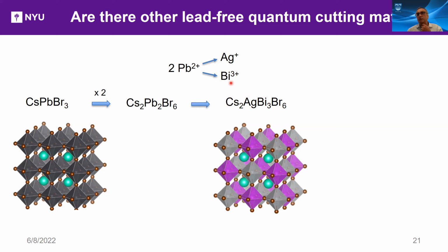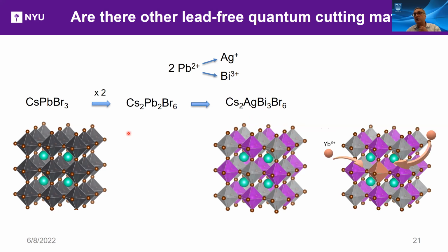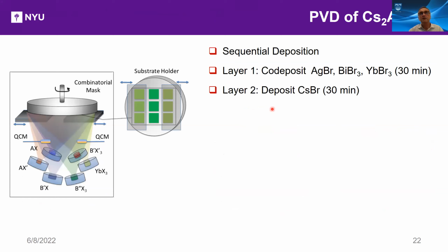So the compound that we're talking about is called a double perovskite, because it comes from this derivative by doubling the unit cell. And we're going to do ytterbium doping, and ytterbium can substitute into either the bismuth or the silver. If it does substitute into the silver, it might have to form defects as well to keep the vicinity charge neutrality, whereas it's an isovalent substitution on the bismuth. So I will talk about this material.